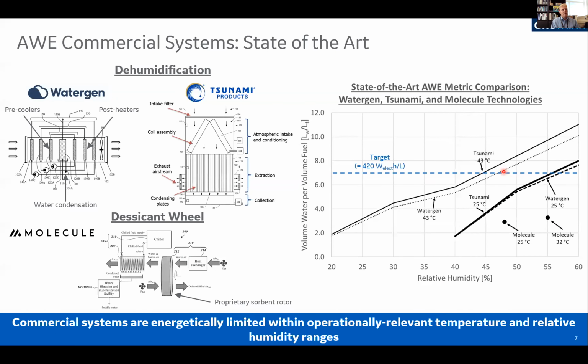So you may be asking, well, what about commercial systems and what is the state of the art? There are a number of really wonderful and elegant systems out there, from WaterGen and Tsunami products, which use dehumidification, as well as Molecule, which uses a desiccant wheel. The problem is that many of these commercial systems, particularly dehumidifiers, are only operationally feasible at higher relative humidities, greater than 40%, if not 50% relative humidity, and in a narrow temperature regime.